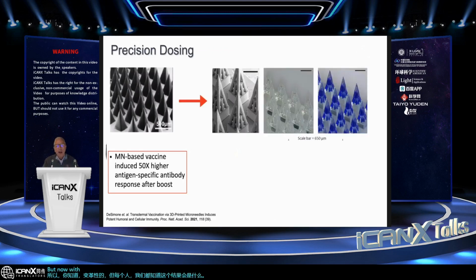But now, with our high-resolution printer, we're making needles we couldn't have even dreamt about in the past. And these are lattice microneedles with much higher surface area per needle, with new kinds of functionality. We can coat the needles with solutions that dry and leave a coating on the needles. But very excitingly, we can trap droplets of liquid through controlled interfacial tension in each needle. And we can deliver the liquid, mechanically protect the liquid in a lattice and deliver that into the dermis.